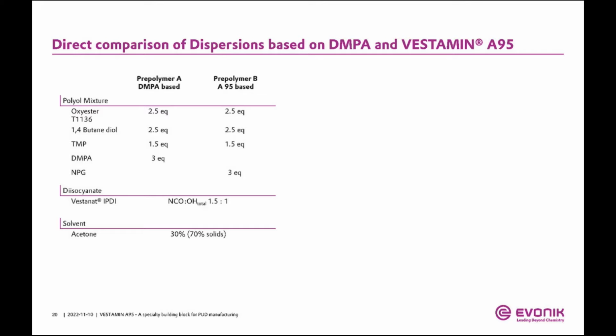So we wanted to really have the exact same formulation. As you see here with the prepolymers in this table, in both cases we have taken the same long chain building block, which is a polyester with a molecular weight around 1000. We have another short chain building block, the 1,4-butanediol, both with exactly the same equivalents. We have some TMP in there for some branching of the PUD.